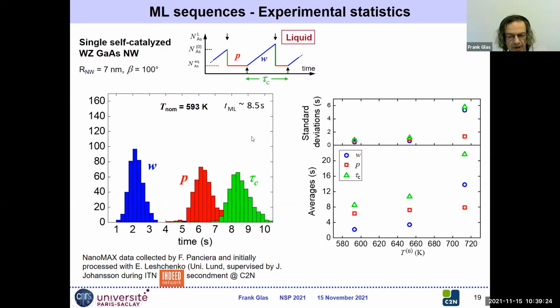And a very important quantity also is the monolayer cycle. So between monolayer completions, which are here, we have this tau-c time. So we have this experimental histogram. There are average values if the growth conditions are stable, but because it's still random, we have a certain width to the distribution of these characteristic times. And we have this at 3 temperatures. So these are the variation of the average position of these characteristic times and the standard deviation.